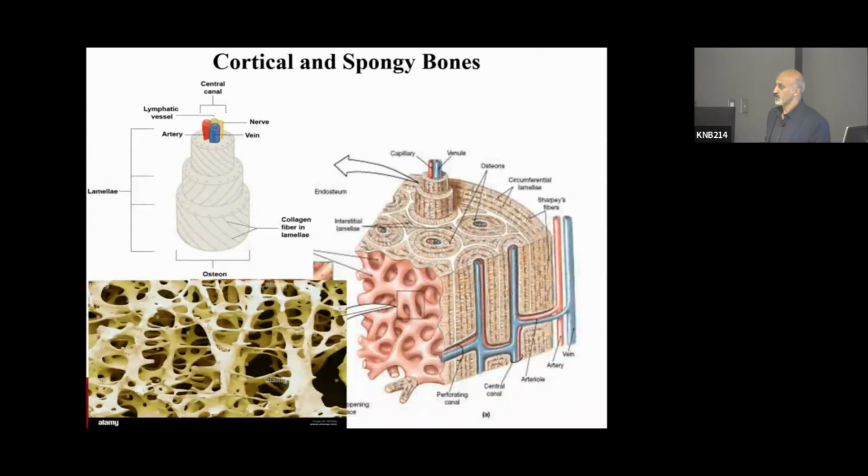In each osteon or Haversian system, we have a combination of hollow cylinders called lamellae, 20 to 30 lamellae. We can see just microscopic porosities in cortical bone. In the cancellous bone, as you can see, we can have very large porosity. In the case of osteoporosis, it can be even up to 85, 90%.